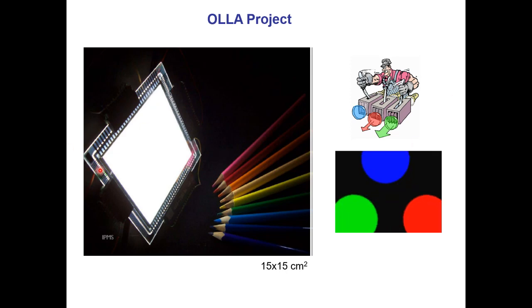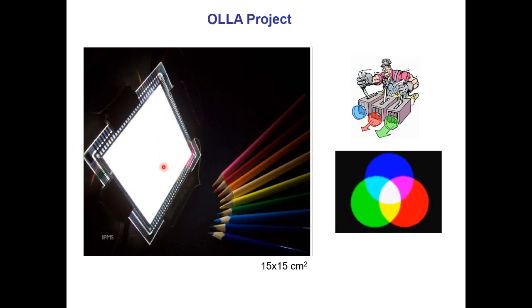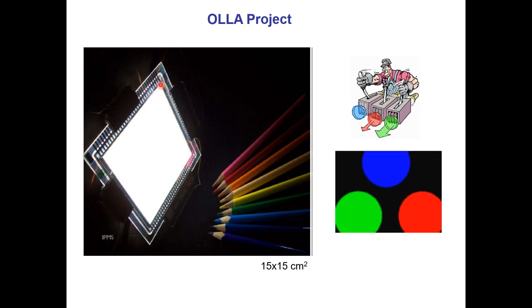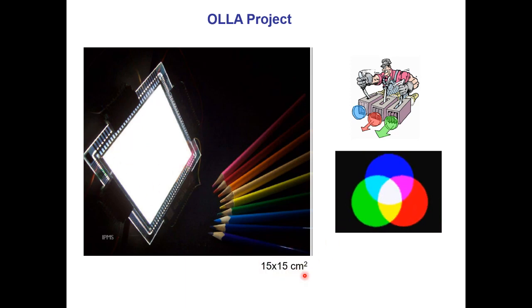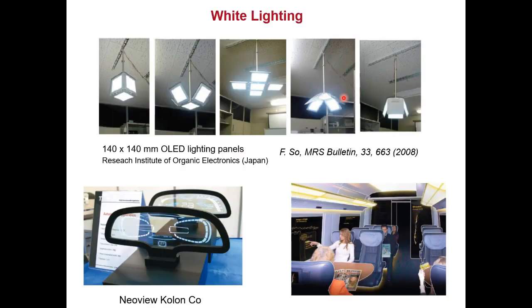This is an example of a panel emitting white light, and basically the main problem of OLED is that you cannot inject a large current, and so the brightness is not as good as a LED display. And this is why, to compensate, people are playing with significantly larger areas for the white panels. It's about 15 by 15 centimeters square. And right now there are some products starting for the designers to make huge panels on walls, to make ceiling lighting panels. This is already sold in Japan.